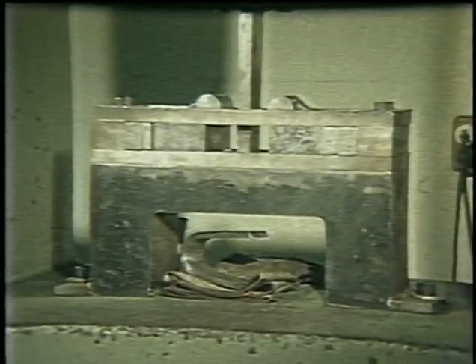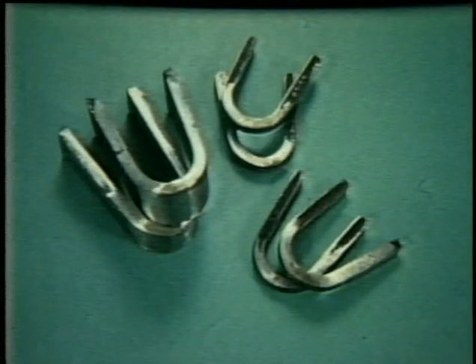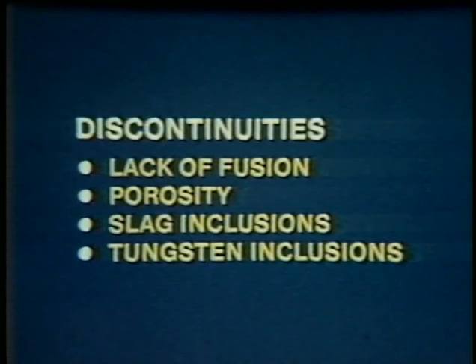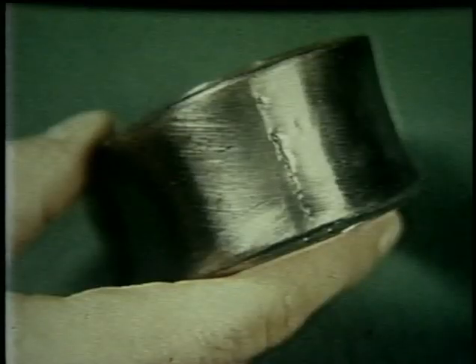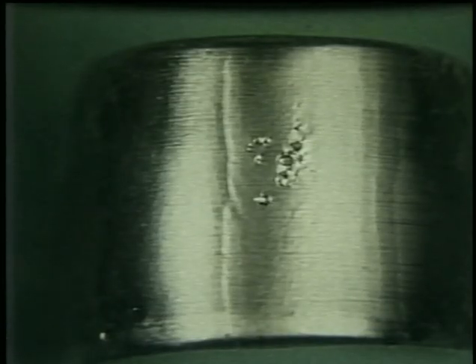Once all the required specimens are bent, the evaluation process begins. The standards of acceptability differ with each code, so care must be taken to use the proper code. Discontinuities may appear during bending due to a lack of fusion, porosity, slag inclusions, or other weld problems. Those exposed on the convex surface are evaluated according to acceptability standards. Some codes require that discontinuities on the sides be evaluated as well. Any discontinuities greater than the allowable code limits are considered unacceptable. As an example, the maximum size for porosity could be 1/8 inch, measured in any direction.